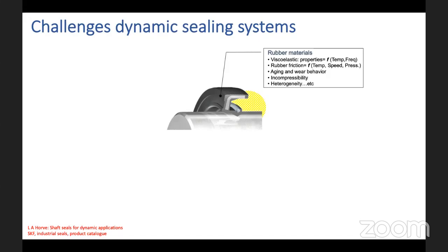For optimizing tribological performance, you have to optimize many things, because in tribology you have to optimize the system properties. Here you see that the rotary lip seal is made up of rubber materials, and it has its own viscoelastic properties, its own friction properties. It can age, and it's heterogeneous, so there are many variations in material properties. And then you also have to optimize the lubricant if you want a good sealing system which does not leak and gives low wear and low friction. You have to use a good lubricant.